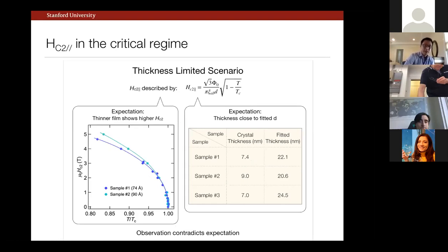We don't have that much of a thickness variation that we can access given the stability constraints that I told you about earlier. But certainly we could easily see these variations in, for example, other geometrically confined superconductors. Doesn't make any sense. And the final comment I could make is for those with expertise, spin-orbit coupling can also change this simple interpretation, but that is going in the wrong direction, actually. That should give you a thickness underestimate and not the other way around. Sorry, let me just let it ring. Hopefully that will go away.